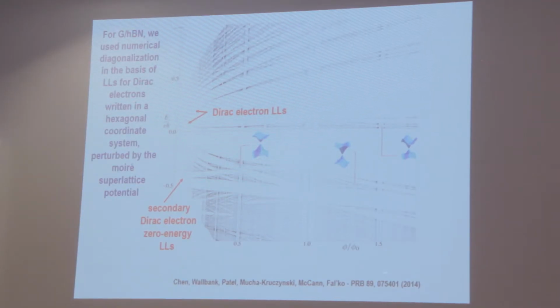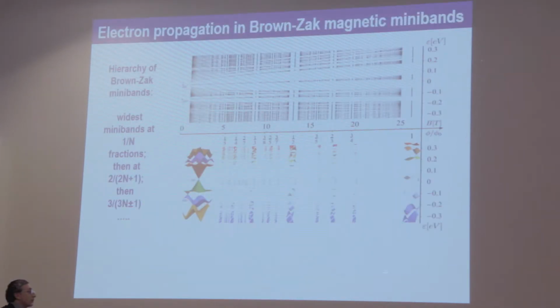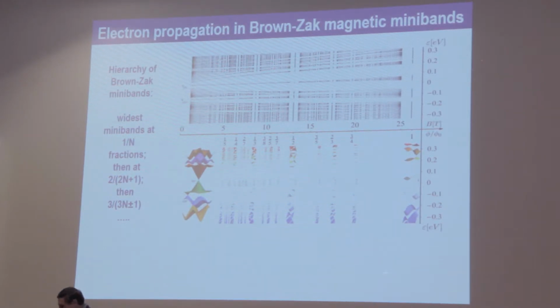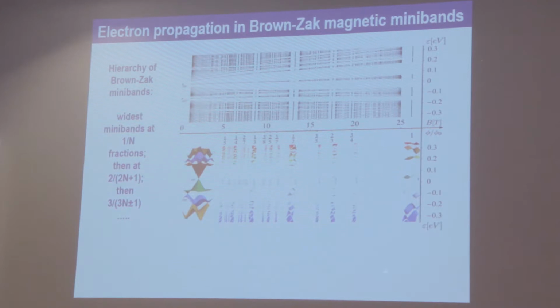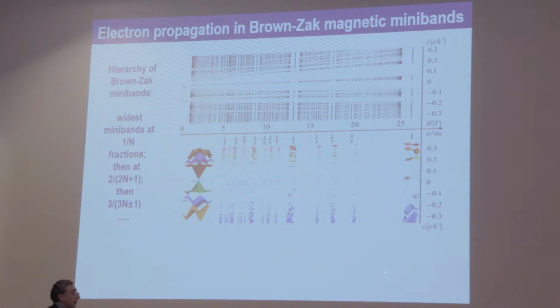superlattice. But also what we paid even more attention to were the electron dispersions in those minibands, in those small Brillouin zones that we get for each of the values of p over q for which we are able to do enough calculations to get the miniband spectra. And those miniband dispersions are actually quite important because those represent the hierarchy of the spectrum in the system and give a chance to observe the traces of the Hofstadter butterfly directly and even at pretty high temperature.